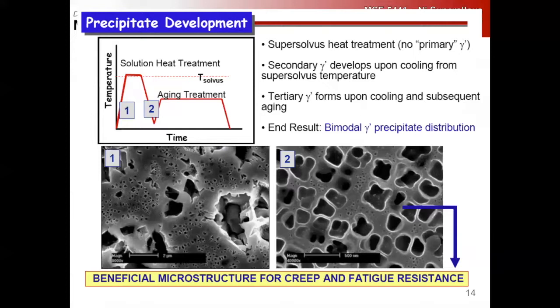Upwards of 80% gamma prime fraction, right? And so if you think about a dislocation in the gamma trying to move through this minefield of gamma prime particles, this boulder field essentially, you can see the sort of tortuous path that it has to take. So the cooling rate from here to here is going to have a huge effect on the microstructure, as you can expect, right?